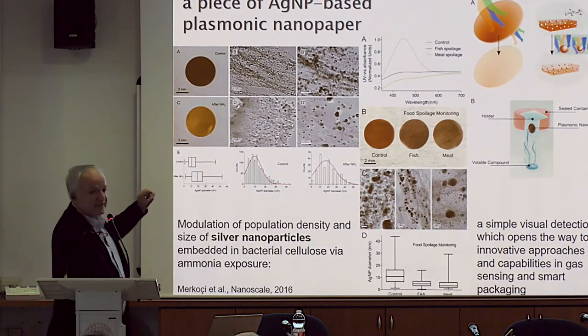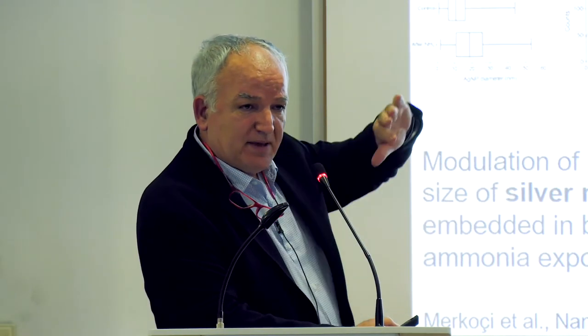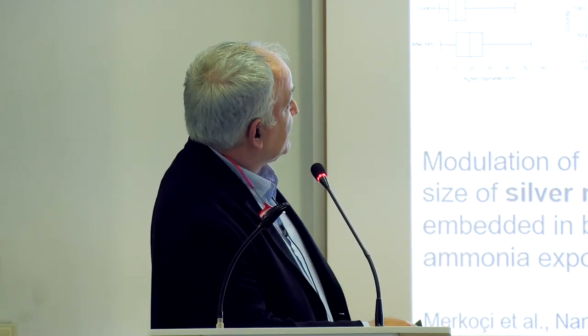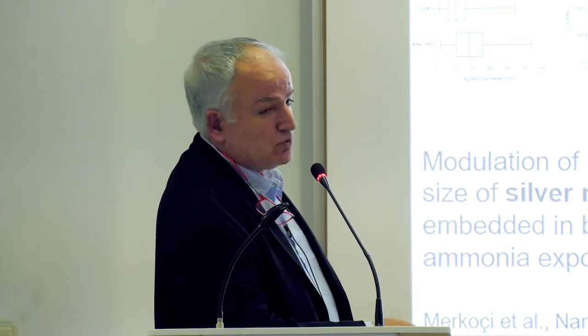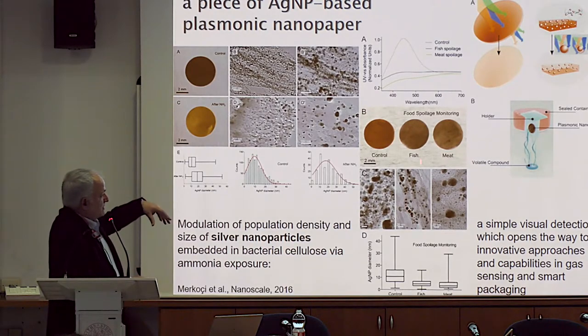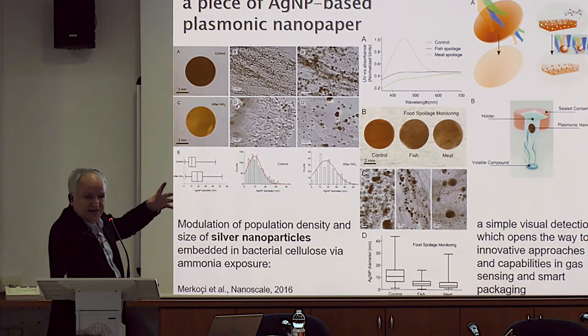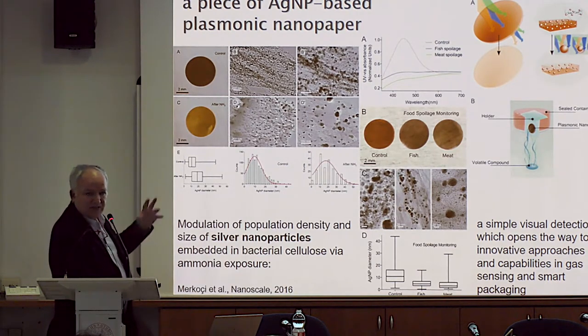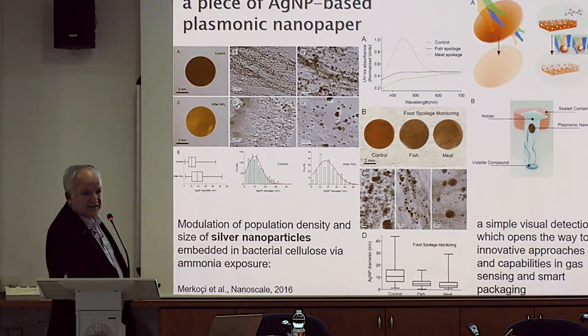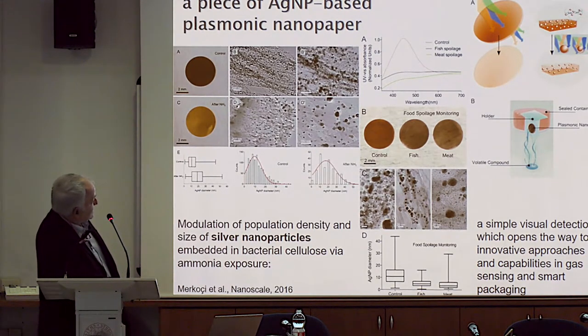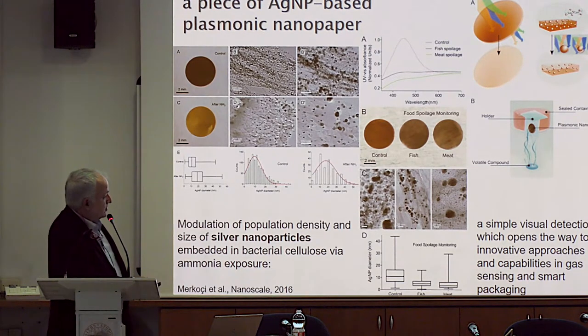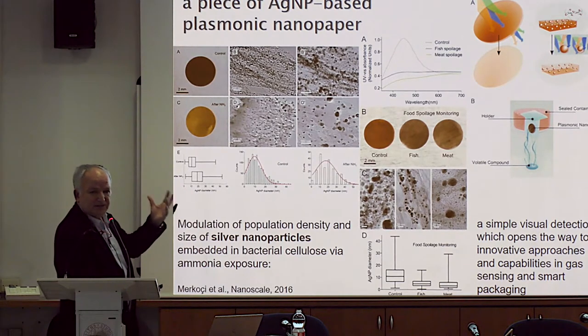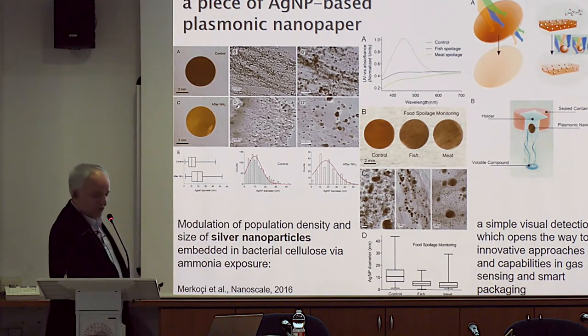I'm just moving. And this is a nice example with smart packaging. So this nanopaper, which is modified with silver nanoparticles, we use this to detect food spoilage. So we put this in contact, for example, with fish or meat, and during the degradation process there are some volatile compounds, usually amine-based compounds, that interact with silver nanoparticles, corroding these silver nanoparticles. And as you can see here, there are changes in the color. So, for example, control or fish or meat spoiled. So we use this and we offer this as a simple, smart material that can show the quality of the food.